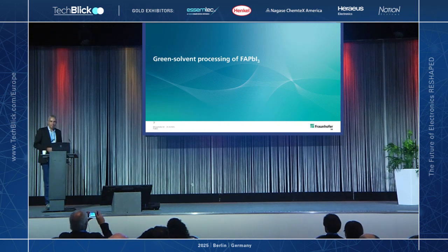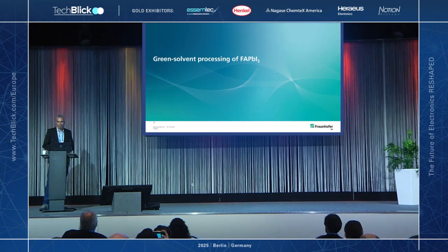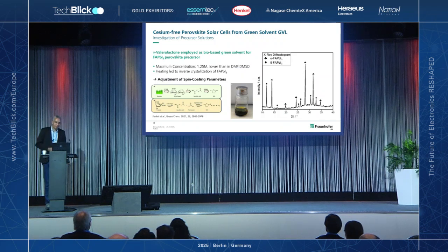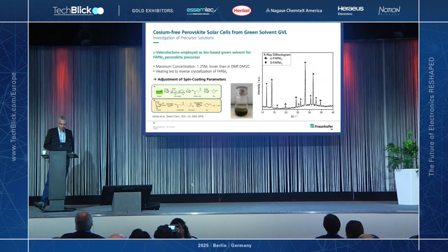Starting with green solvents, we chose to work with green solvent processing of a cesium-free perovskite, FAPbI3. And we chose to use gamma-valerolactone as a solvent for that, GVL. This is nothing new, but it's a very green solvent, as green as can be, because it's also bio-based. You can, in a few synthetic steps, synthesize this solvent from biomass or fructose.